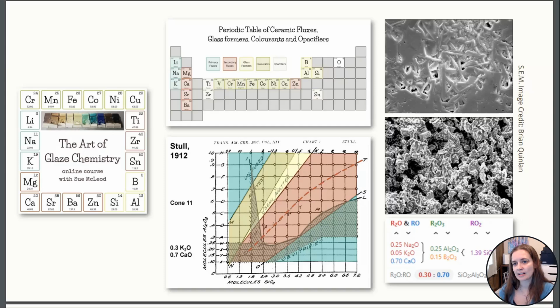And so if your matte glazes are underfired, they're more susceptible to leach, to break down over time. Going in the dishwasher with hot soapy water can really speed up the process of breaking down a glaze that isn't durable and has not properly formed a glass yet.